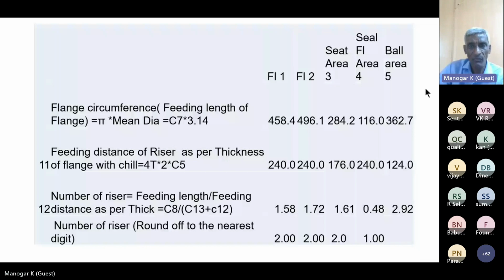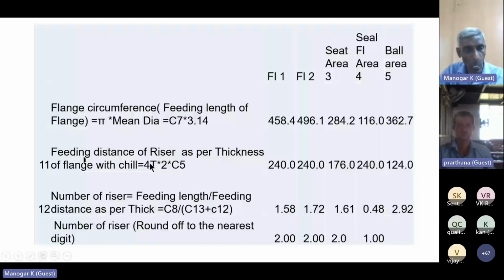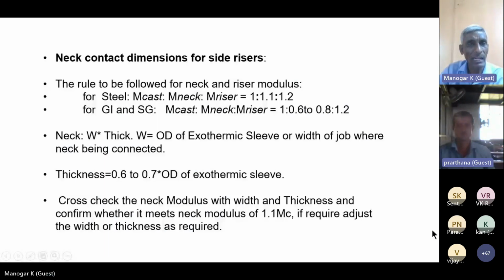So here the flange circumference is 458, the feeding distance of the riser is 240, that is 4 times the thickness. Number of risers required is 1.5, so round it up to 2. Like that, for all the 5 sections we arrive at the risers. Neck contact dimension for the side riser, we already said the neck should be 1:1.1. So calculate the neck, which should be equivalent to the OD and thickness of the casting.